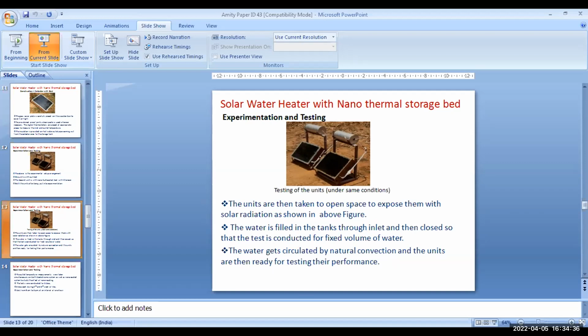So these are the 2 solar thermal systems we have fabricated. One is provided with an additional bed filled with nano copper oxide material, which gives better results compared to the solar water heater without that bed. So this is the idea. We could also measure the radiation input energy. We did 2 units to measure at the same time, so that we can prove which one is better. By having 2 similar units prepared with the same parameters, we are able to conclude that one unit is giving better results compared to the other, which is not provided with the thermal storage bed.